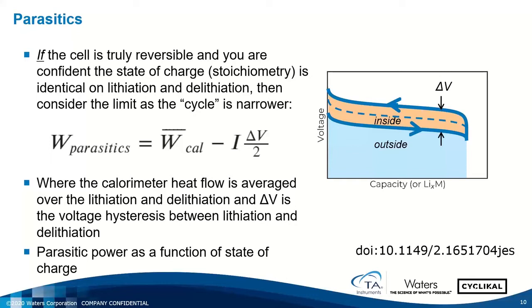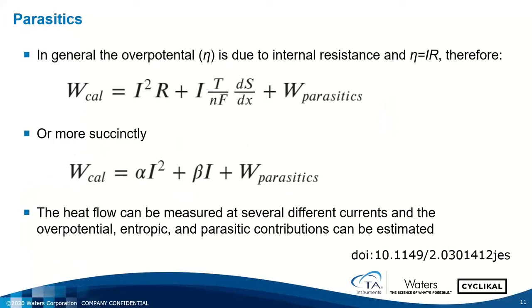And then this gives me an even stronger handle on what are the acceptable ranges for cycling, or where does my particular additive decompose. So we've seen taking it full cycle, narrow cycle, instantaneous point in state of charge. And if we want to take it even a step further and completely characterize the functional form of the heat flow coming from the calorimeter, we can do that in certain circumstances by noticing that the overpotential is typically a function of current.